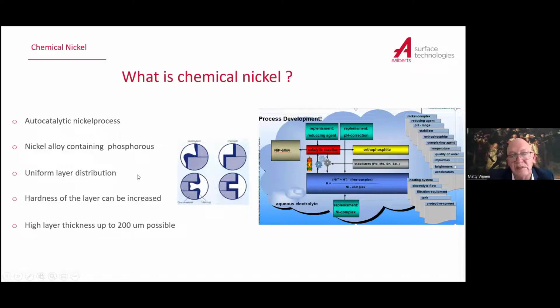The big advantage of this process is that it gives you a uniform layer distribution. That means that everywhere where the solution is the same and the part and the temperature of the bath is the same, your layer will be the same. That means in holes, in recessed places, on edges, so you get a very good layer distribution. Due to the fact that phosphorus is in that layer, we can increase the hardness of the layer. And that means increasing the hardness will also increase the wear resistance. A layer thickness up to 200 microns is just about possible.